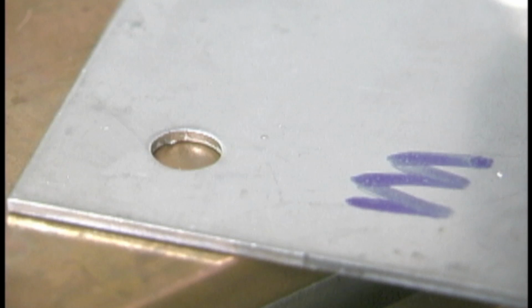You remember last week's video, we talked about using copper backing for filling holes in some thin stainless steel, and how it traps argon and also provides a heat sink. Well, it works good on aluminum as well, and on this particular job, it worked really well. Here's the little repair filling the hole on stainless steel. A small hole like this, there's no point in stopping. You just fill it all in at once, but it traps argon on the backside and is almost as good as having argon shielding on the backside.